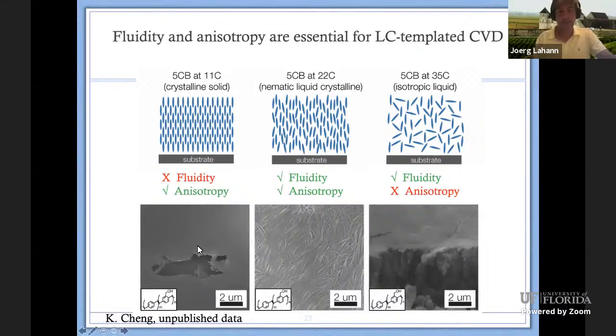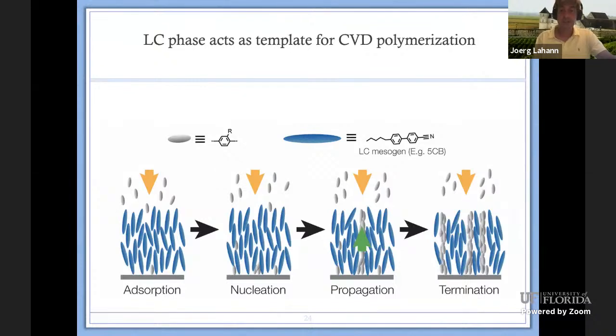So this is what you get with crystalline. This is the isotropic phase. This is the nematic phase for the same LC. I kind of went over the mechanism already. What we think is happening, it's still not 100% clear, is that we diffuse the monomer in here. The monomer has to combine with another monomer on the surface. So you get some initial polymer oligomer hills, so to speak, formed on the surface that induce defects. And then these defect lines act as a guidance for the polymers to form.